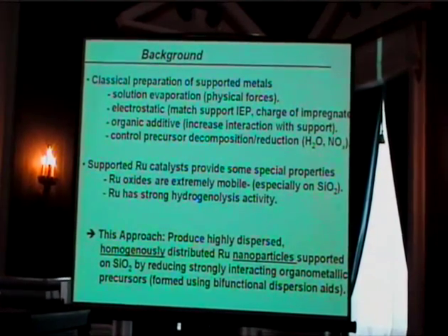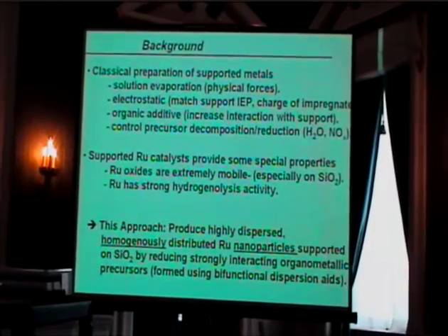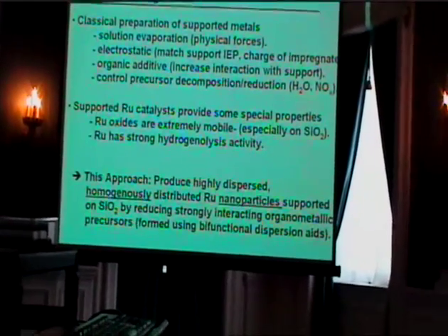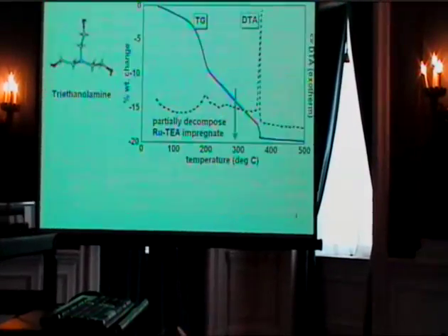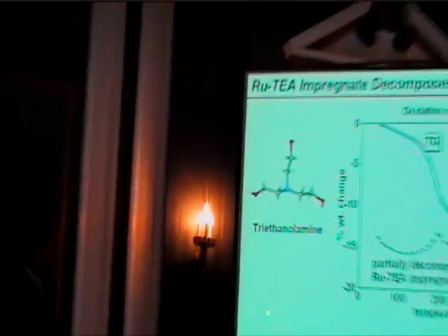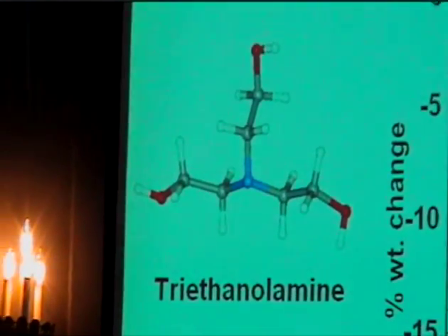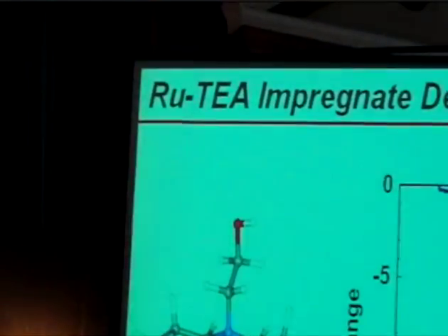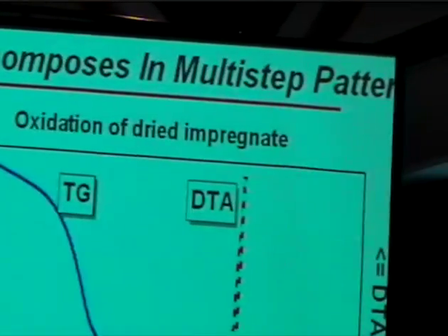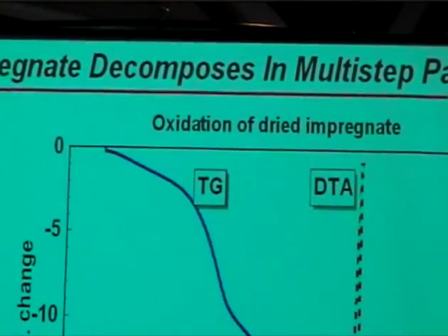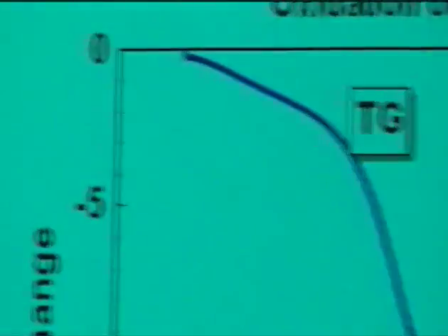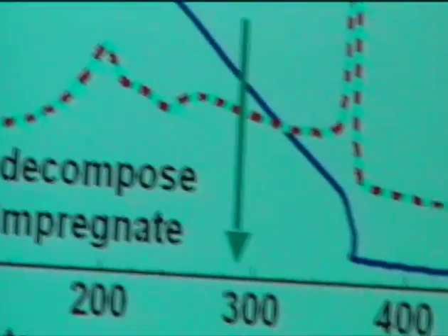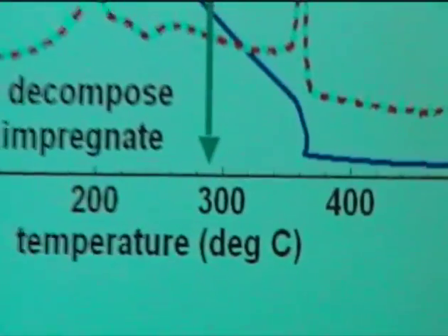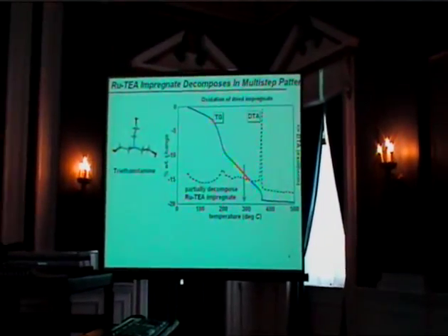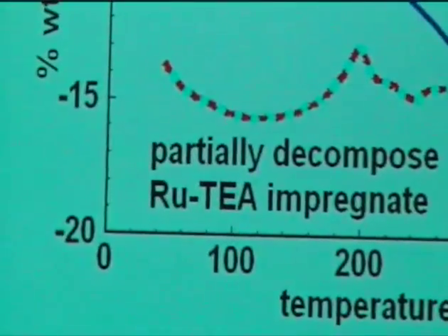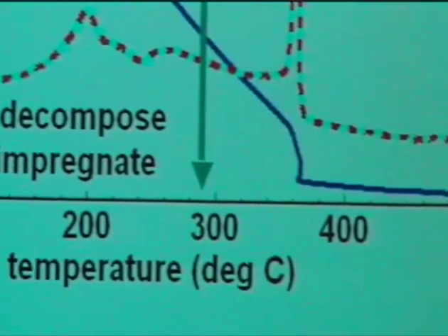So we're going to do that by forming in situ, and I'll use the term loosely, some supported interacting organometallic precursors, which were formed using bifunctional dispersion aids. Well, it's a kind of a wordy sentence, but I'll show you. It's actually a very simple concept. The reason we got to work on this was the idea became, a lot of the organics that people use in impregnations are monofunctional. They have carboxylate groups, they have hydroxyl groups. So we started to work with bifunctional dispersion aids, things that would have an NH2 group and either an OH or a COOH group. So this is one, and this is the one I'm going to be talking about today, triethanolamine.